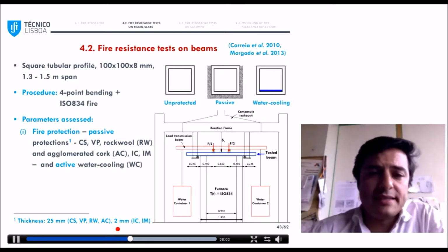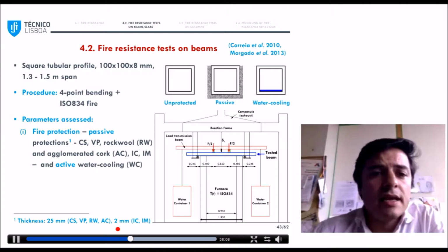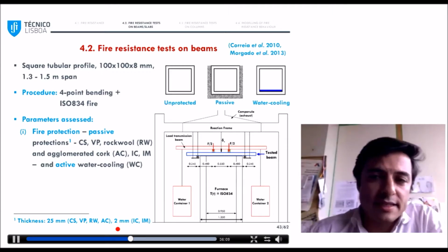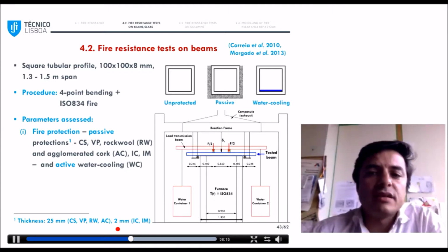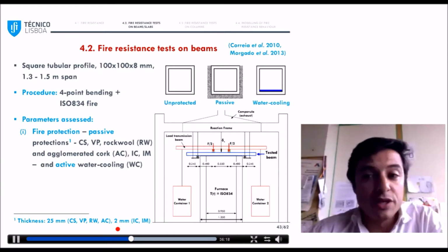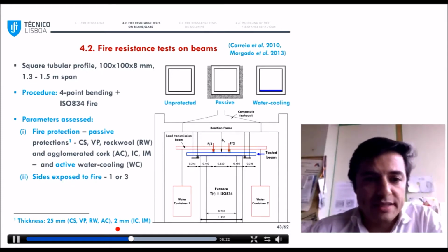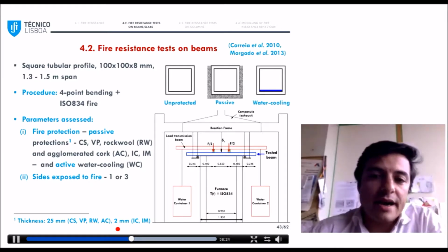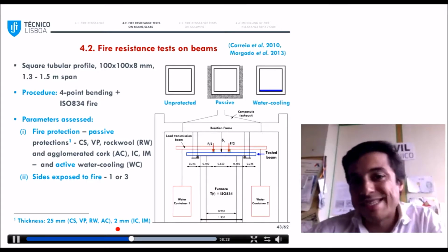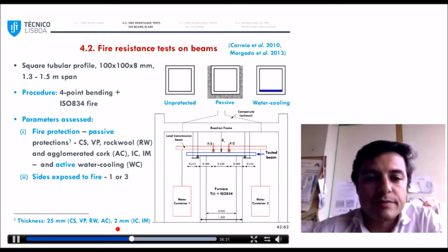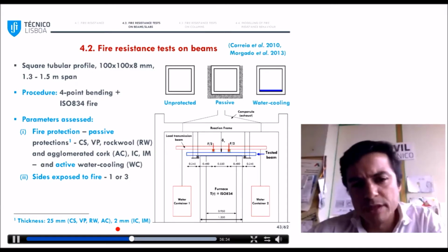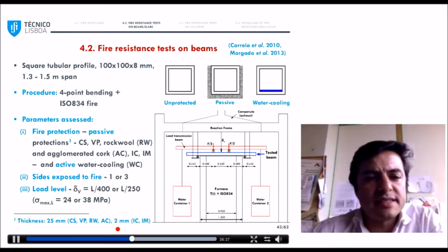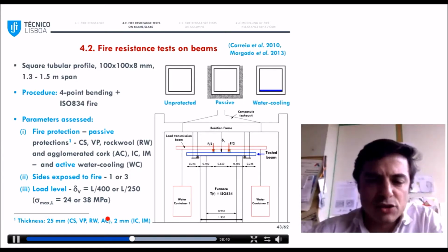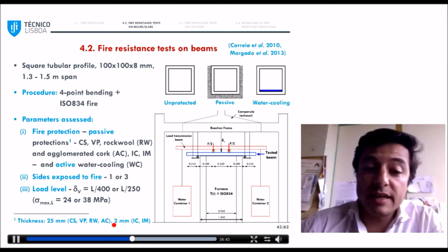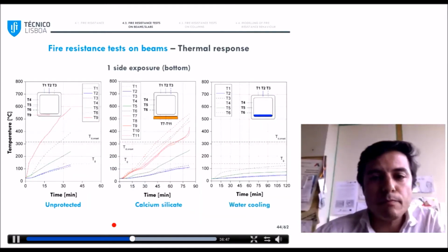In terms of parameters, we tested different passive protections as panels or as an intumescent paint or mat. And we also checked water cooling, which had been successfully tested at EPFL a few years before. We also evaluated the number of sides exposed to fire, either 1, so only the bottom surface, so as a slab, or 3, the bottom and also the sides, so more similar to a beam. And we also tested 2 different load levels expressed in terms of mid-span deflection levels.